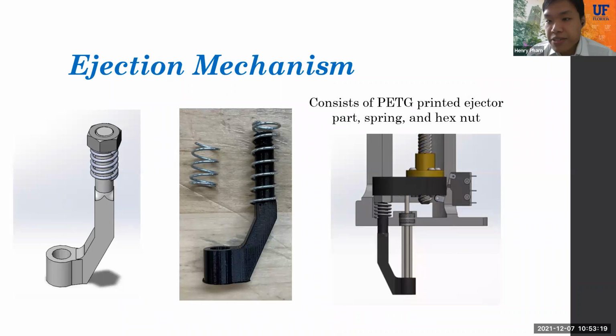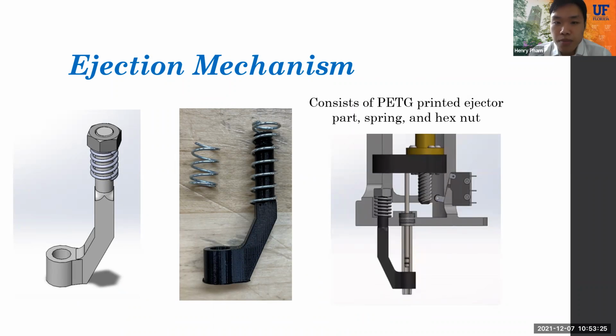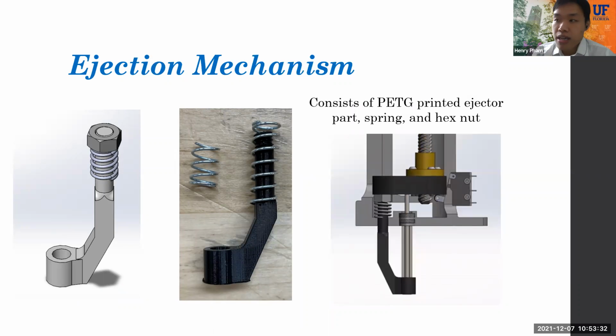So for our ejection mechanism, we use a 3D printed part, a spring, and a hex nut to eject the disposable pipette tips. The 3D printed part was printed using PETG plastic at a 100% infill due to its strength. And the 3D printed part consisted of a sleeve that wraps around the pipette and a threaded end to attach a spring and hex nut.